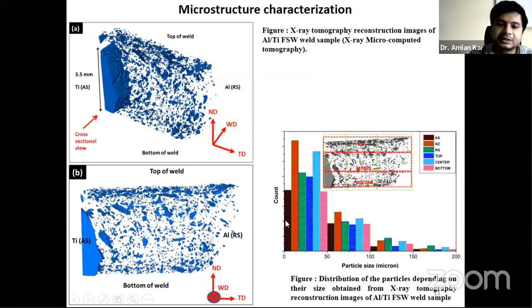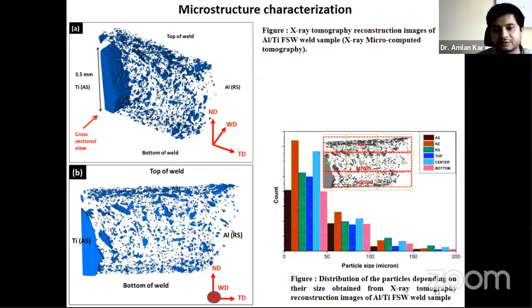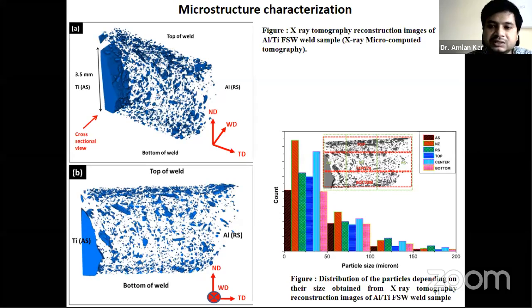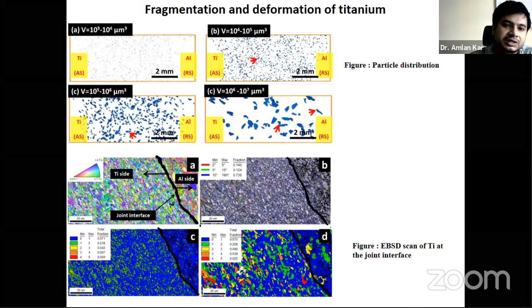There is a possibility that the coarse particle which is developed initially could be subjected to further fragmentation, and that will lead to the formation of smaller or finer particles. Therefore we can expect that the finer particle counts have increased in each location, and we have seen the very same thing over here. A similar approach we can see over here also. So the fine particle fraction, or the number of fine particles, is very, very high compared to the coarse particles.